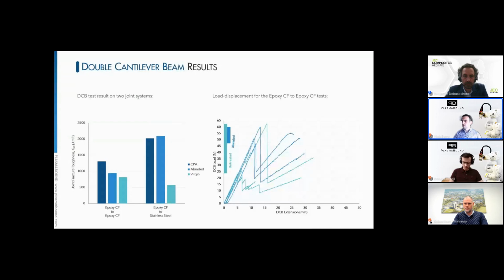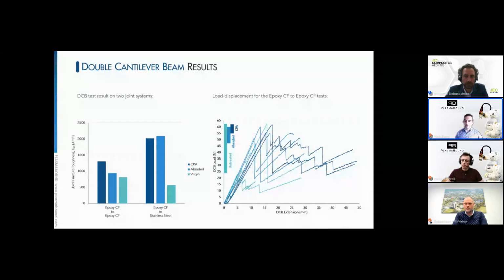And what I mean by that is this sudden and very quick decline or reduction in the strength integrity. When it comes to the CPA prepared surfaces, our grouping is much tighter, but also fails more progressively. No longer is there a cliff edge failure, but there's actually this progressive over time failure. This progressive failure means that there might be a forewarning that failures are going to occur in an in-service scenario.